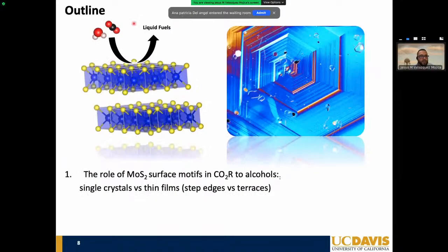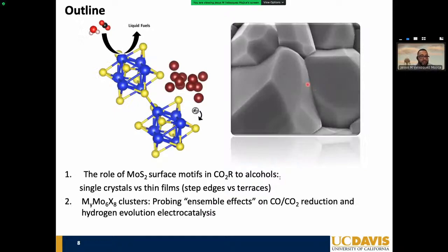As I've hinted before, we've been able to successfully tune these discrete areas within the extended solids, and I will give you all these different updates as we go. So we will talk about surface motifs of molybdenum disulfide. As you can see here from the optical image, depending on the synthesis that you choose, you could control screw dislocation, edge sites, and vacancies on the surface. They all have a role to play in the electrocatalysis reaction. We will look at these active sites for the Chevrel phases.